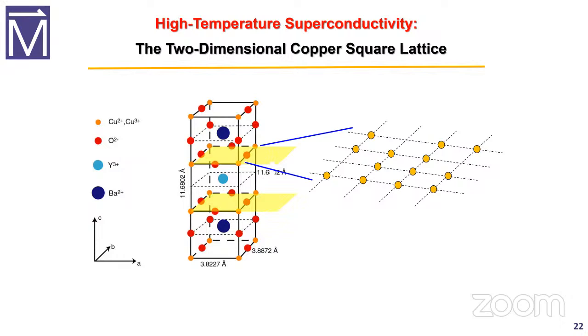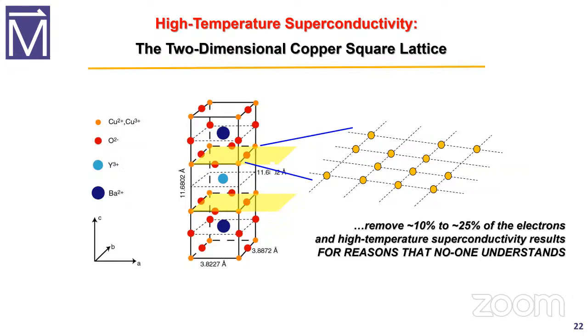Now we'll move to the copper square lattice. You start with a copper square lattice, and you put one electron on each site, each copper, and then you remove about 16% of them. And for some reason, in the range of about 10% removed to 25% of the electrons removed, you get high temperature superconductivity for reasons no one understands. This was discovered in 1986, became well known in 1987.